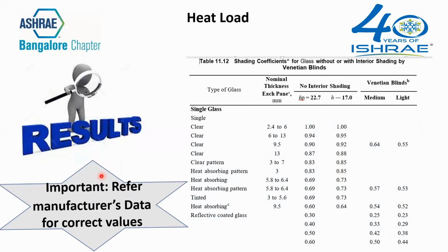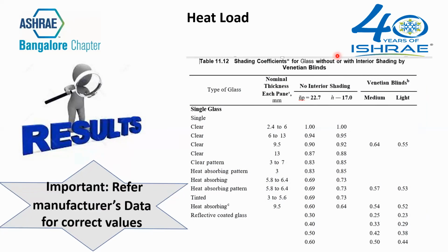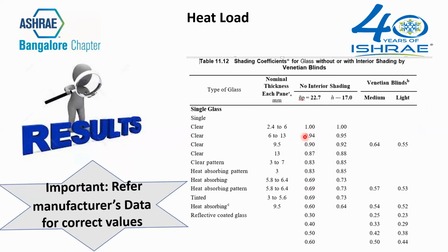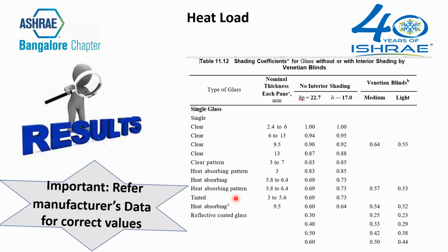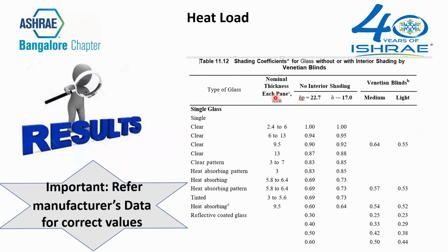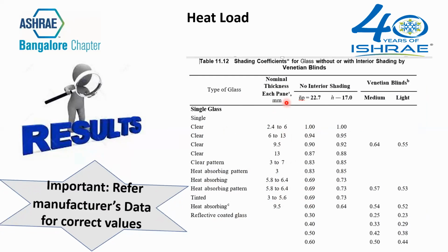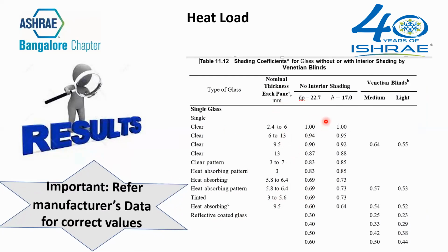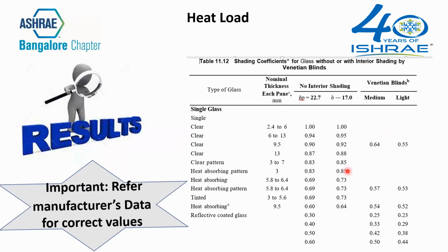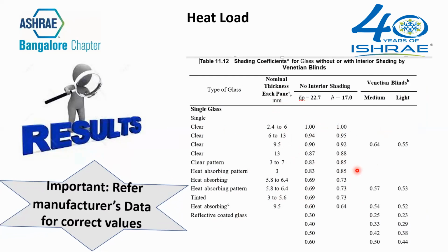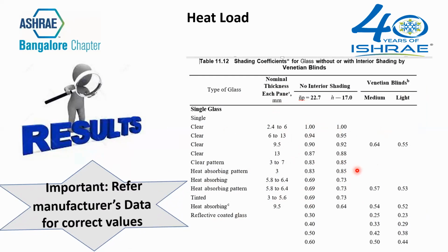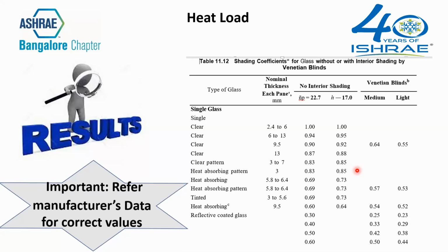So what are the results? If you look at the results here, if you look at the watt per square meter, what we are considering, if you look at the various types of glasses, what we use, single pane, thickness, interior shading with Venetian blind, if you look at the watt per square meter, it has reduced drastically when you compare it with the previous table of 11.11. And when you compare it with the 11.12, however, please note, I have something which is very important here, which I have mentioned.